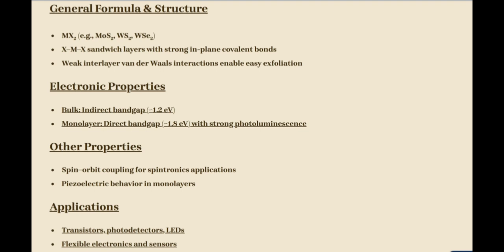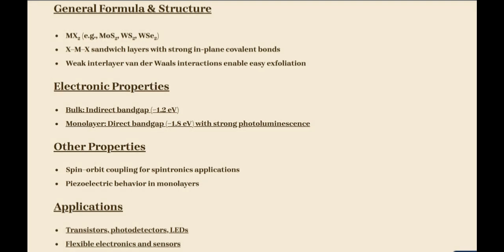Structural and electronic properties. In TMDs, the layered X-M-X structure plays a crucial role in determining their electronic properties. In bulk form, these materials generally show an indirect band gap. However, when reduced to a single layer, they undergo a transition to a direct band gap. For example, monolayer MoS2 has a direct band gap of around 1.8 electron volts. This transition leads to strong photoluminescence and makes monolayer TMDs very attractive for photoelectric applications.